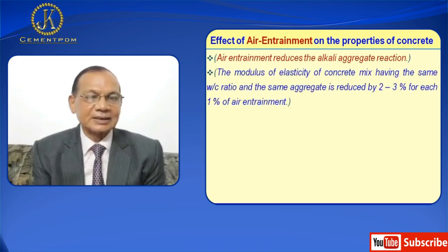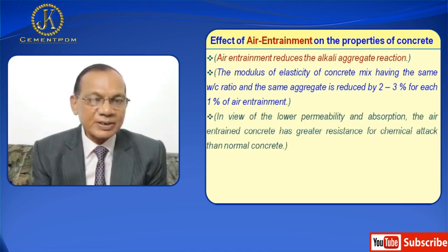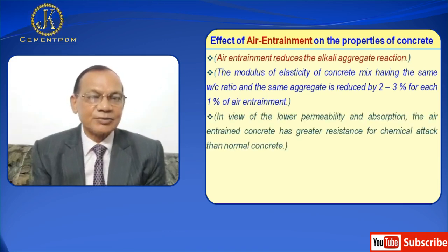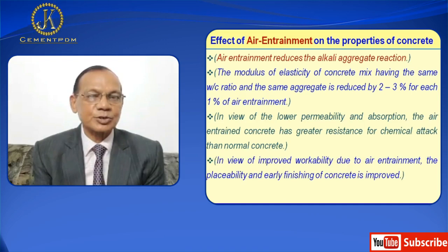Air entrainment reduces the alkali-aggregate reaction. The modulus of elasticity of a concrete mix having the same water-cement ratio and the same aggregate is reduced by 2 to 3% for each one percent of air. In view of the lower porosity and absorption, air entrained concrete has greater resistance to chemical attack. Due to improved workability from air entrainment, the placeability and early finishing of concrete are also improved.